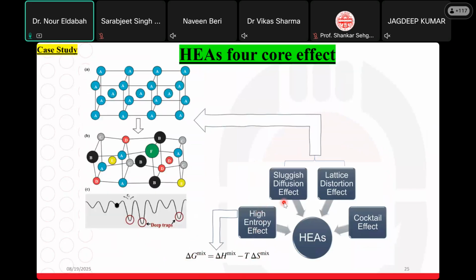Sluggish diffusion and lattice distortion are two effects. When we have different atomic sizes inside our alloy, fluctuation in the potential will oppose any migrating atoms. This will increase the time needed for an atom to migrate from one place to another, and in terms of processing high entropy alloys, we will need a very prolonged time for thermal treatments. And the cocktail effect: we are using at least five elements for the high entropy alloy, so the properties will follow a rule of mixtures from the constituent elements.